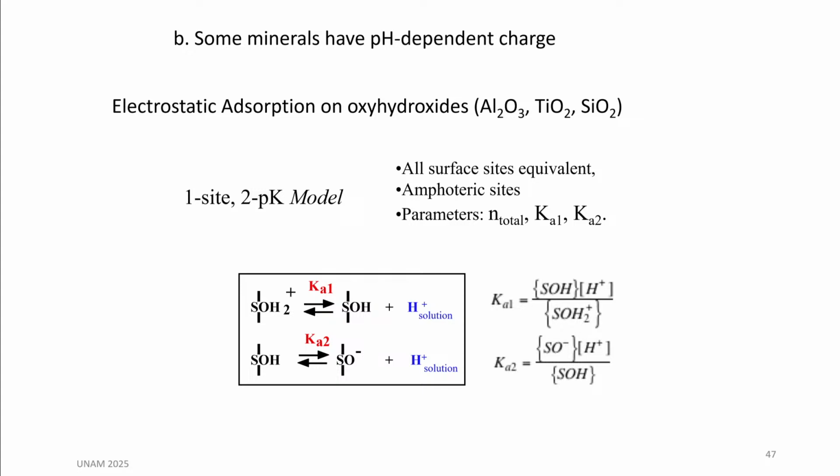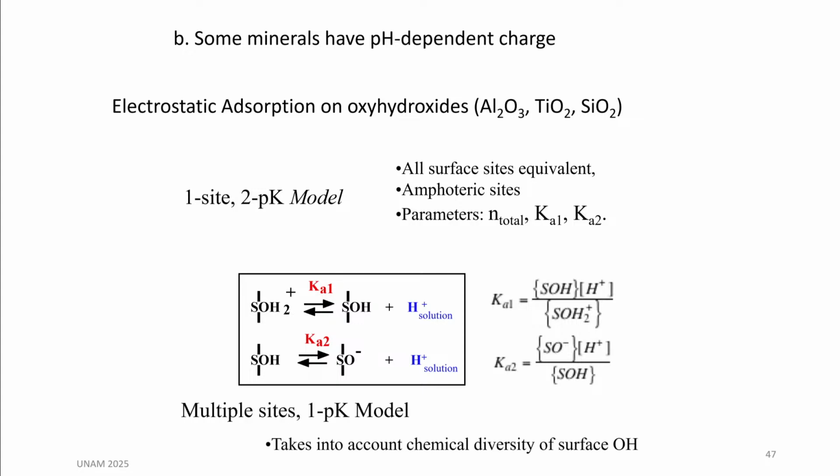If on the opposite, the pH is inferior to the point of zero charge, it means you have a lot of protons, you are bringing in some products of these two reactions, you are drawing the equilibrium to the left, and then you are making positive charges. We see that we will have a positive charge for pH inferior to PZC, and a negative charge when it's superior to PZC.